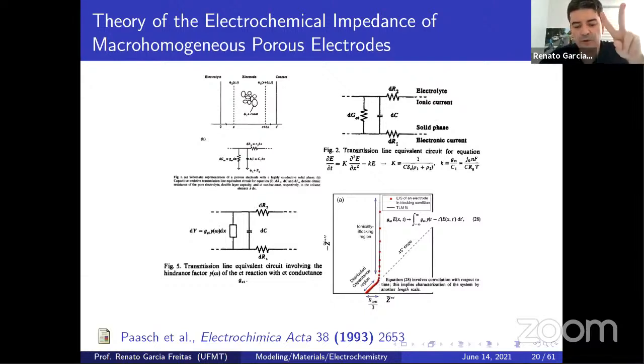You have two hindrance processes considered here for Paasch, namely control of the charge transfer by finite diffusion. We have a finite diffusion of a species getting inside the pore, and the formation of the pseudocapacitance. As soon as this species goes inside the pore and attaches to the surface, we have the charge storage on a molecular scale. So here we have the transmission line. The hindrance term is this one. The rate equation of I is the hindrance, this part here. And the equation is this one, G.